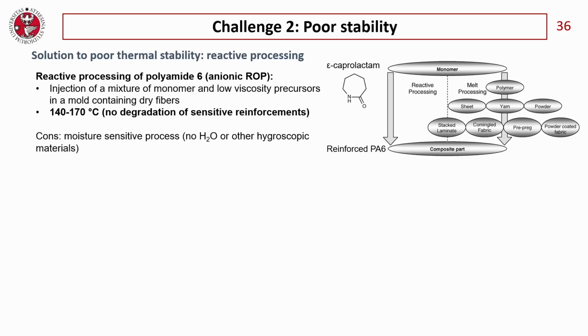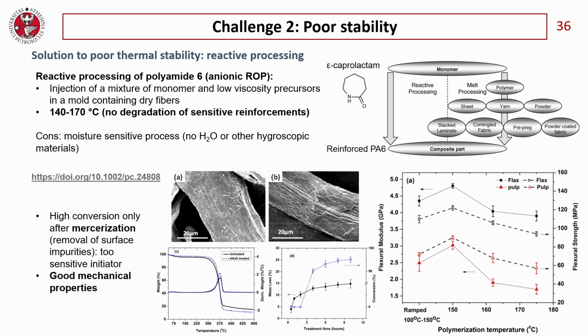Now, you can start from the monomer, from the low molecular weight and low viscosity precursors, and you can inject the monomer directly in the mold, with the mold containing the fibers already, in the presence of some initiators and some catalysts, and in total absence of water and moisture, otherwise this will not work. You can end up with a PA6 matrix composite reinforced with your natural fibers, as it can be observed, for example, from this paper.